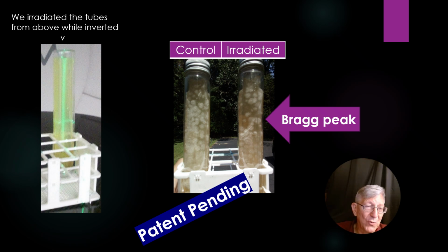Now, take note, when we did the experiment, we actually inverted these tubes. This was like our first experiment. And so we inverted this tube, lined it up properly, and the proton beam came in from above. The metal cap is at the bottom, and based on our calculations, based on the density of the agar and all that sort of thing, we assumed that the Bragg peak would be somewhere about where the tube enters into this tray that we created.